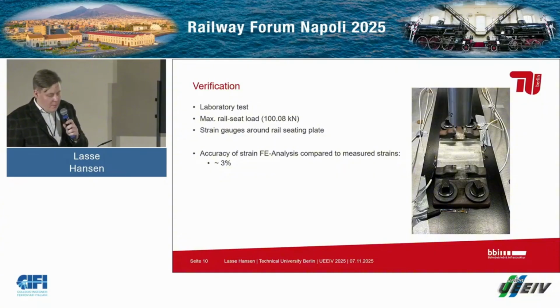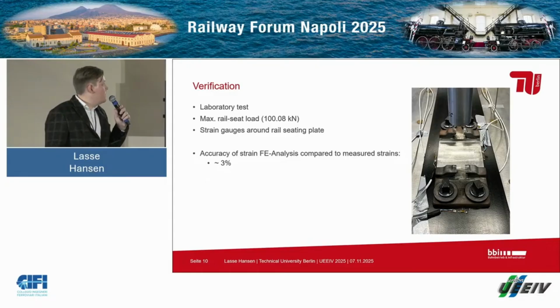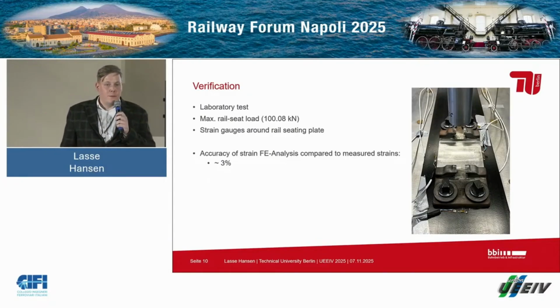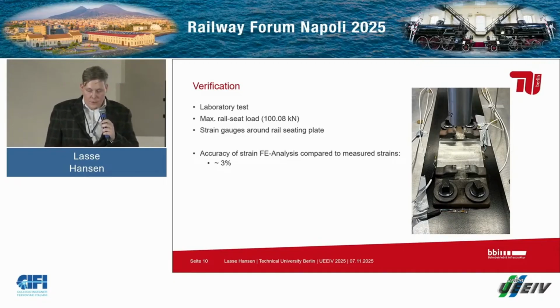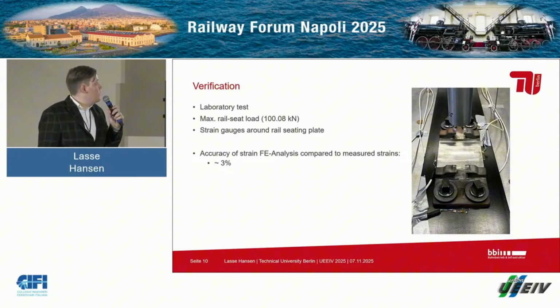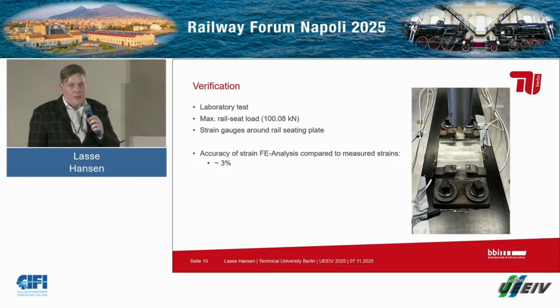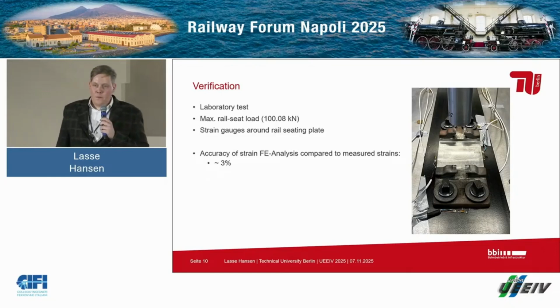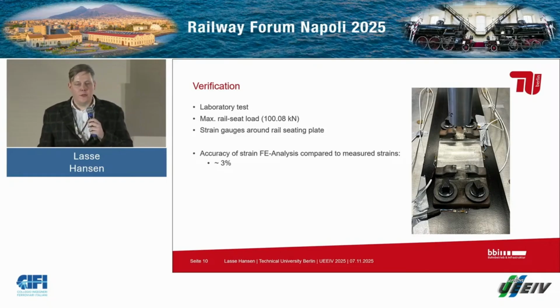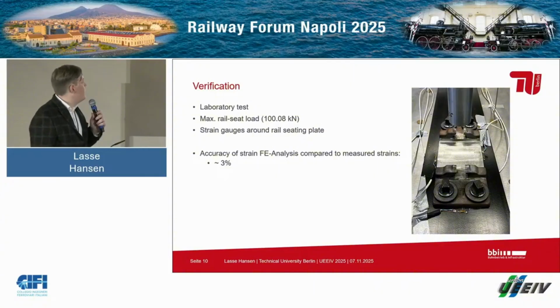As I said, we also did the verification. As you can see, we have rail seats, the current normal seating for polymer sleepers. I know Foslo is doing some research and production with direct fixations, but for our lab test we had to use these rail seats, and we applied the maximum rail seat load of 100.08 kilonewton, which I showed you before, the highest load. We wanted to get the strains, so we placed strain gauges around the seat, as you can see in this picture, and compared the strains to those appearing in the simulation. We had an accuracy of around 3%, somewhere a bit more, but this was because of torsions.